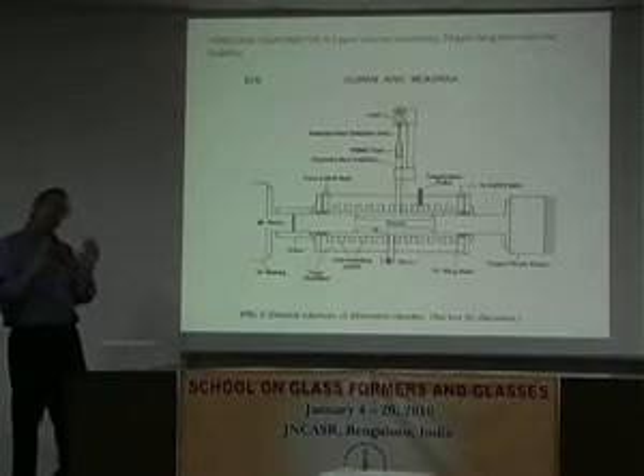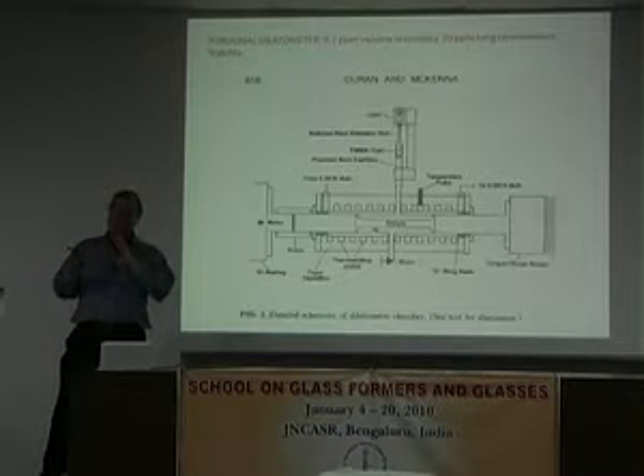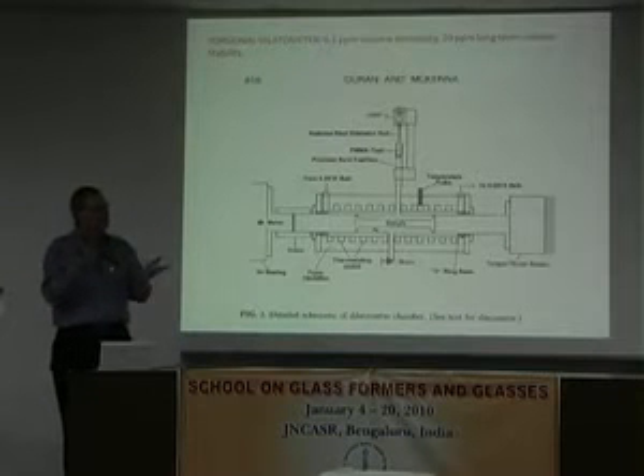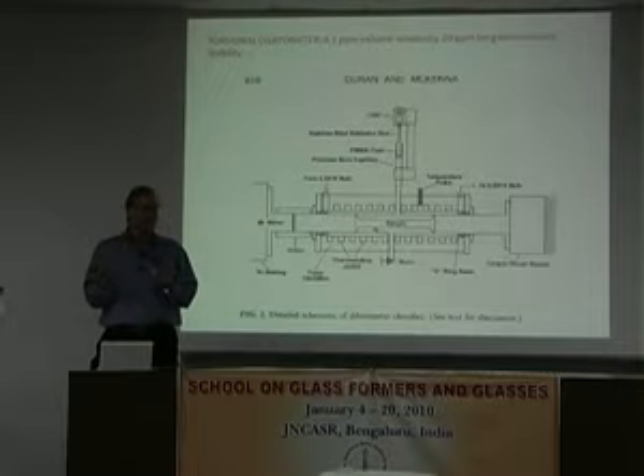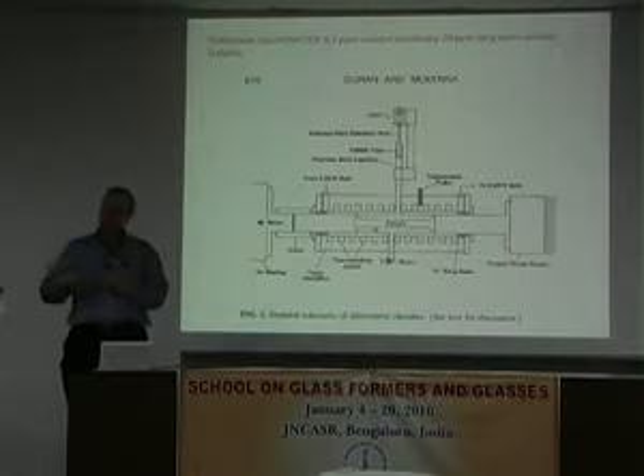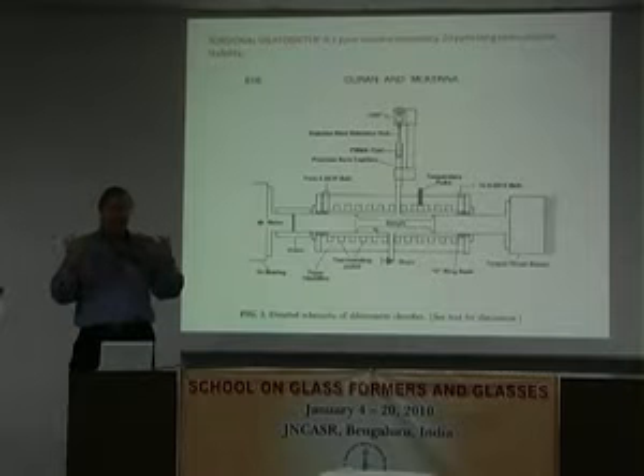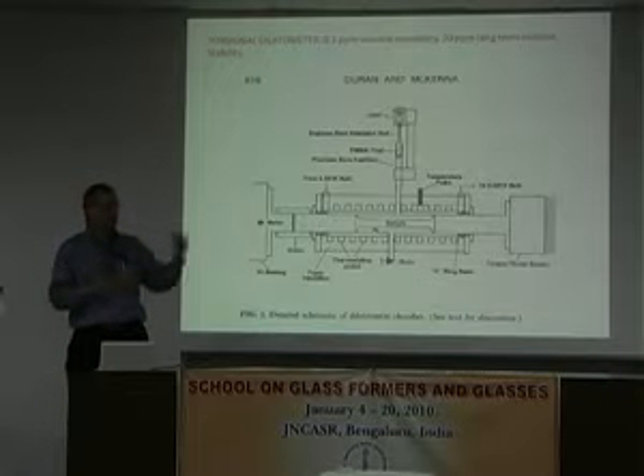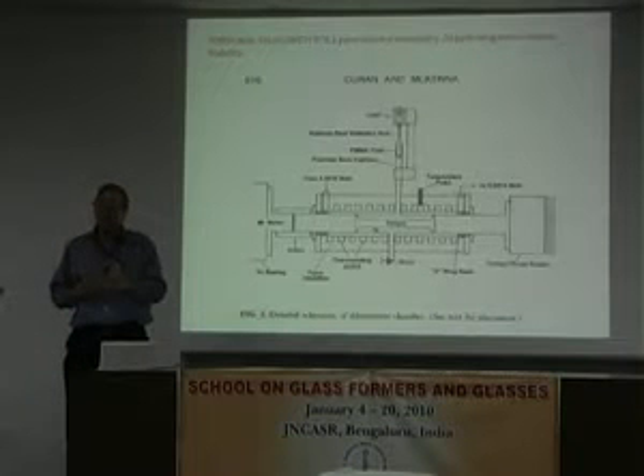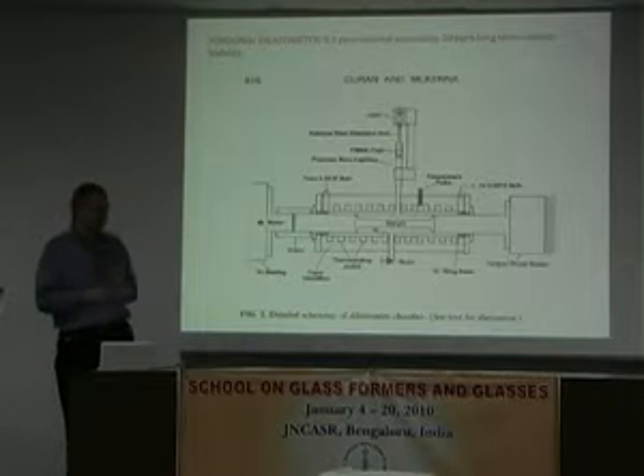So what we decided to do was go to torsion. If you do torsion, volume changes are second order effects. So we expected those to be small, and we would be able to then sort out the underlying volume behavior from the mechanically induced volume behavior. So that's what we did.